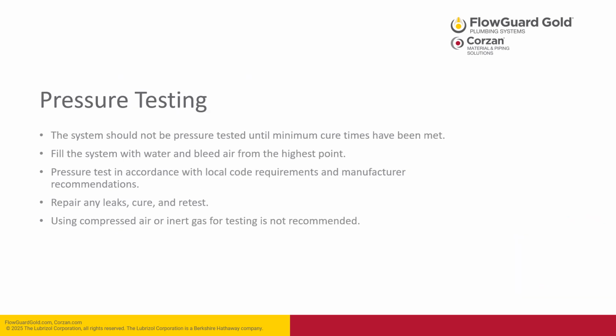The system should not be pressure tested until the minimum cure times have been met. Make sure to fill the system with water and bleed air from the highest point. Pressure test in accordance with local code requirements and manufacturer recommendations. Repair any leaks, cure, and retest. It is not recommended to use compressed air or inert gas for testing under any situation.